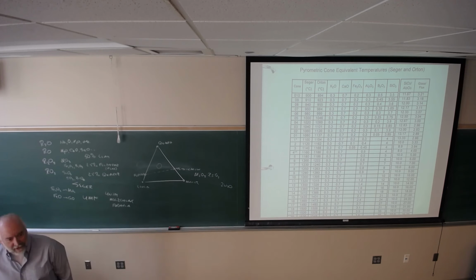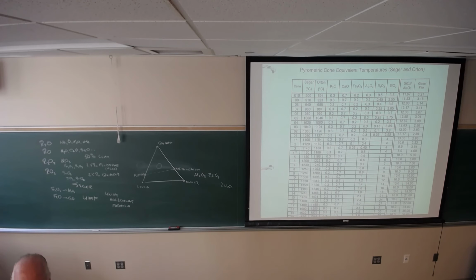Basically theory. All right, so we have this illusion. It's a great illusion. Propels us in our industry, and it makes us invaluable to people making ceramics. And that is that cracking occurs on firing. Fair enough? Think about this. What is wrong with that picture? The argument is, oh, I heated too fast on one end versus the other. Nonsense. It makes no sense at all. If I can take a tile, even if I run it through the kiln with the 3 meters perpendicular to my direction of travel, so you only have 2 meters, you're still talking about that thing shrinking on one end before it shrinks on the other and holds together.